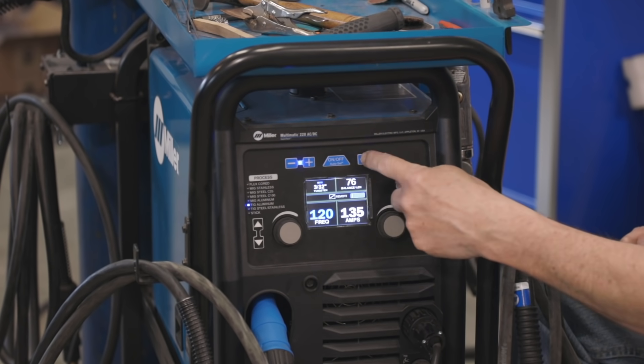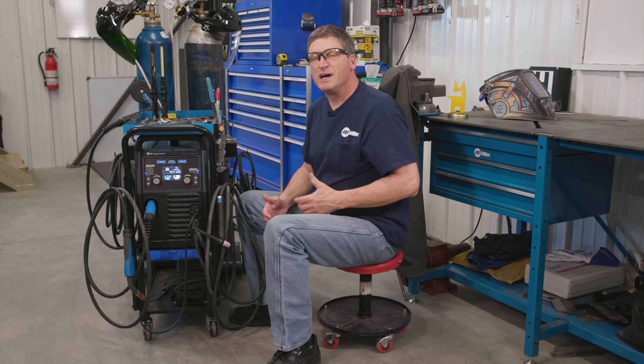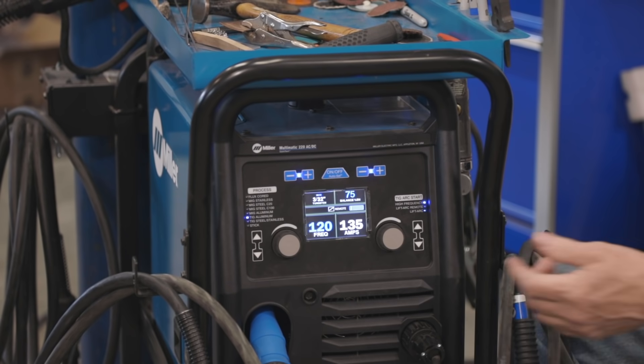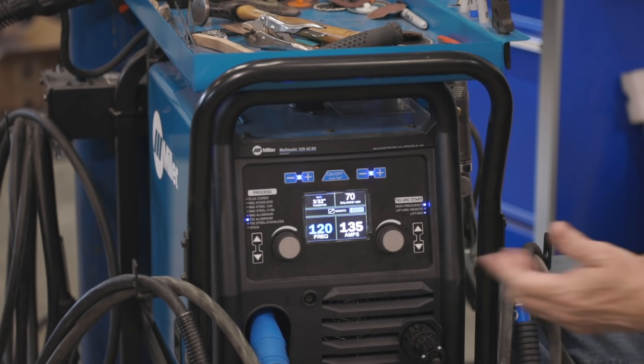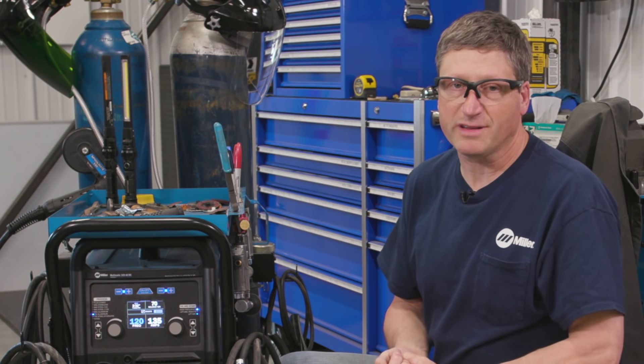The pro set for balance is 75, so you'll notice that 'pro set' will pop up whenever you hit 75. That means 75% of my welding arc is on the electrode negative and 25% is on the electrode positive. The electrode positive is the part of the welding arc that cleans the oxides off the aluminum. So if I lower that number down to 70, I'm only welding 70% of the time and cleaning 30% of the time. The lower you run this number the more cleaning effect you'll have, and you'll notice that because the white etching next to the weld puddle will get wider. Normally you only need enough cleaning for the width of the weld puddle — any more than that is going to be a waste of energy.